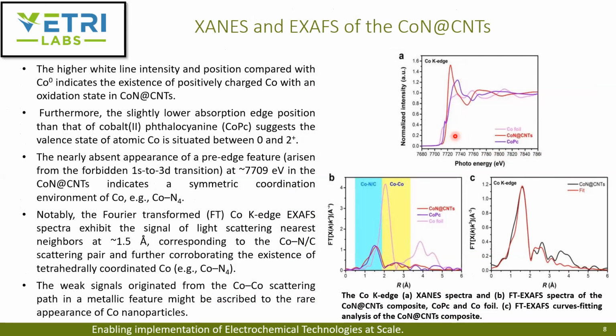And to further give insights on this material, they did the XANES and EXAFS of the material. As you can see here, the higher white line intensity and the position compared to the cobalt foil indicate the existence of positively charged cobalt with an oxidation state in CoNC, like cobalt nitrogen co-doped carbon nanotubes. And further, we can see the slightly lower absorption edge position than that of cobalt phthalocyanine, which suggests that the valency state of atomic Co is situated between 0 and 2+.